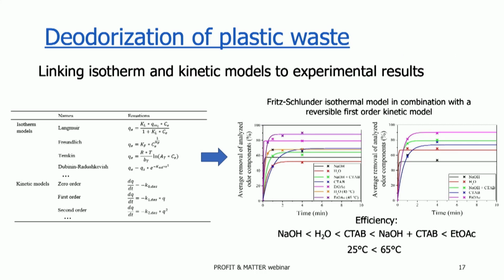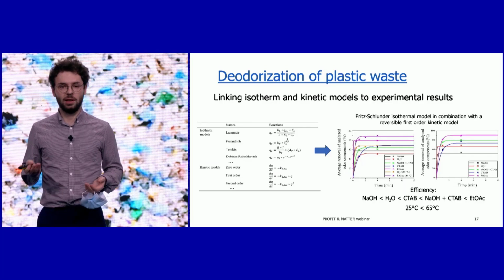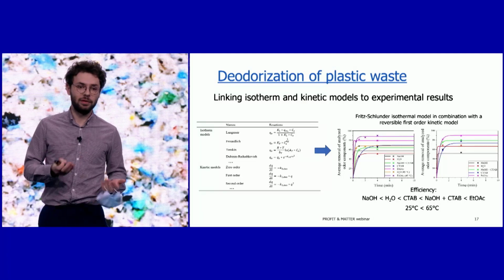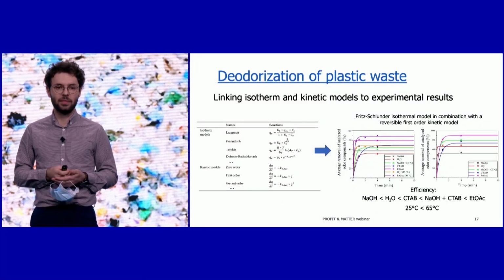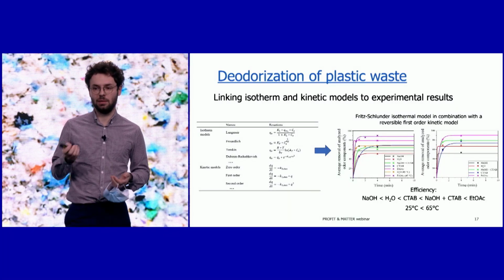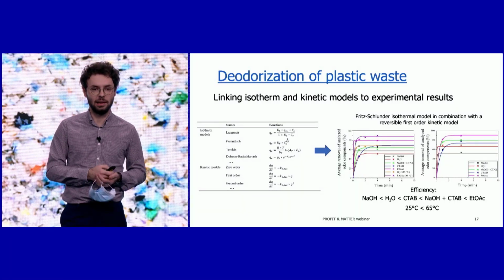As a next step, we linked the experimentally obtained results to a kinetic and isotherm model. We saw that from all the models tested, the Fritz-Schlunder isothermal model in combination with the reversible first-order kinetic model gave the best fit. When we look at the results, we see that sodium hydroxide, so caustic soda, was not so efficient to remove odorous constituents, even less efficient than water, actually. By adding a detergent, in this case CTAB, the removal efficiency was seriously increased. And the best removal efficiency we obtained by applying a solvent, in this case ethyl acetate.